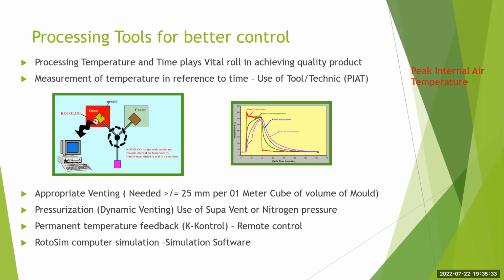Sometimes you are looking for good dimensional tolerances. Normally when you see a water tank, the shrinkage is around 3% to 5%. In a tank, the dimensions are not very important because shrinkage here or there will not make much of a difference in the tank sizing. But when you are going for custom molding and you need repeatable dimensions, then you need to act in a different manner. You need to create pressure in the mold so that there is less shrinkage and you are able to maintain the dimensions.